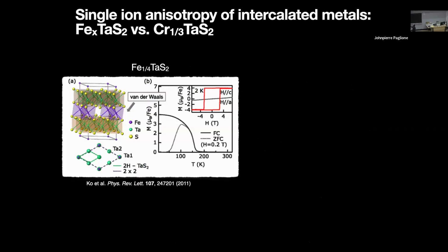We see that play out in iron intercalated tantalum disulfide and iron intercalated niobium disulfide, where for the tantalum case, these are ferromagnets with easy axis ferromagnetism. So the moments are oriented along the crystallographic c-axis, and these are extremely hard permanent magnets. They have a very large anisotropy between the field being oriented along the c-axis and in the plane. For the niobium case, the moments are still oriented along the c-axis. It's just that you have antiferromagnetic interactions, and so you end up with an AFM.